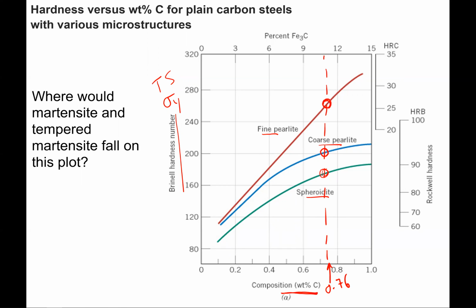All right, so the question is, where does tempered martensite fall in this plot? Okay, so we're going from coarse pearlite to fine pearlite, and then we're going to see where in this plot is tempered martensite. The other thing we notice on this plot is that as the carbon content of any particular microstructure increases, so does the strength. Right? So weight percent carbon goes up, so do our tensile strengths, yield strengths, etc. They also rise. All right, and hopefully that makes sense from the phase diagram. If you think about doing a phase fraction calculation, you'll see the more carbon you put in, the more cementite that you'll have in the structure, and so we expect to have these higher strengths.